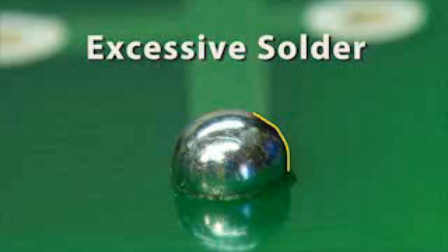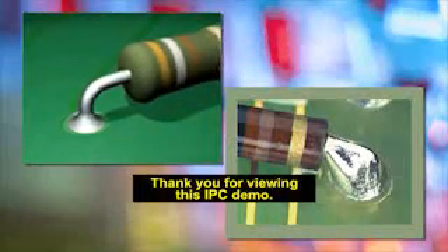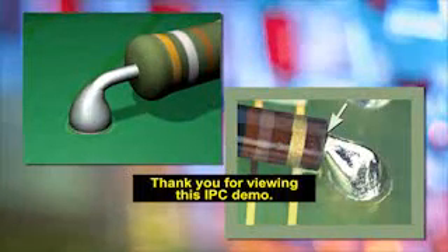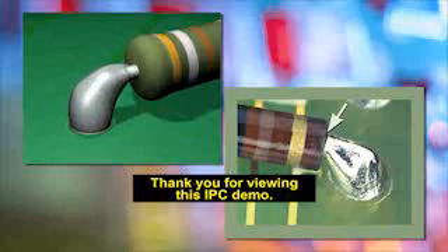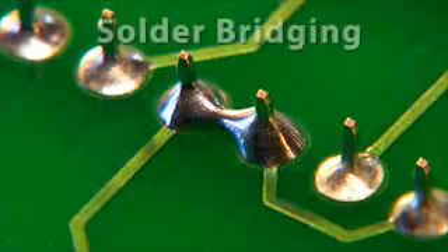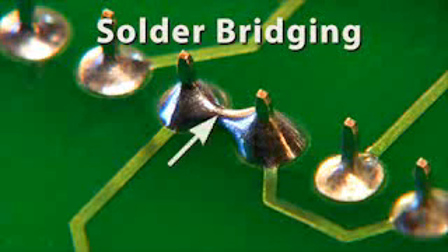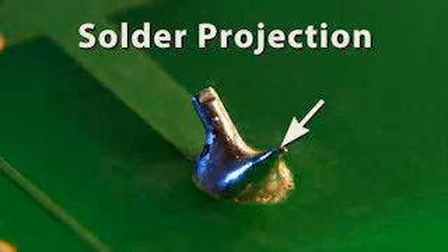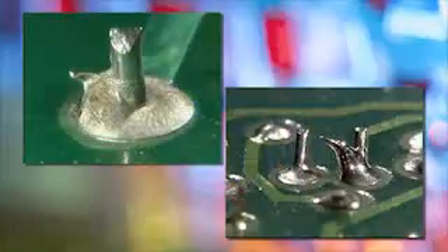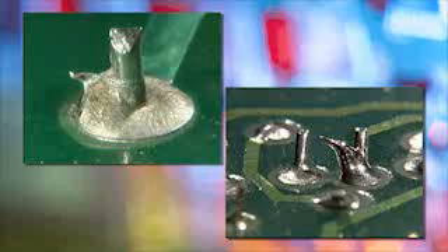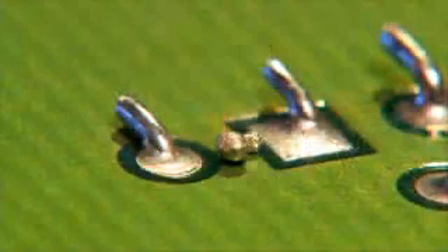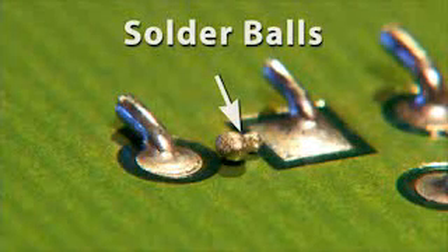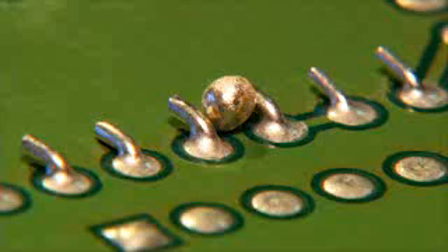The fillet is not concave and there is solder flowing over the edge of the land. Excessive solder can also be detected when solder touches the component body or violates electrical clearance. This condition is called solder bridging. A bridge is an electrical path that was not intended. Here is a solder projection, also known as an icicle or a peak. These are typically caused by excessive solder or insufficient flux, and by the iron being too cool or being removed too quickly. These are solder balls. They can create electrical shorts by lodging in between conductors or component leads.